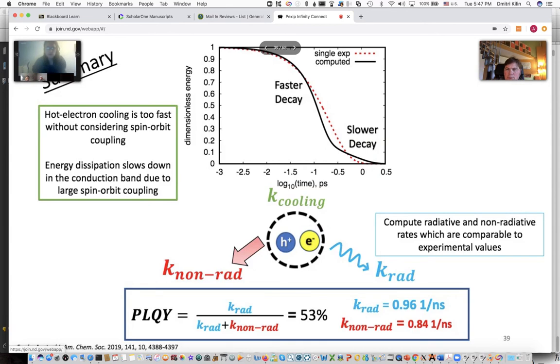And so, summarizing all this, the main takeaways is that without spin orbit coupling, the hot electron cooling is too fast, and that when we include it, we see an interesting slowdown near the band edge. And then from describing how efficient it is, we get results that compare favorably to experiment in terms of the radiative relaxation and the quantum yield.